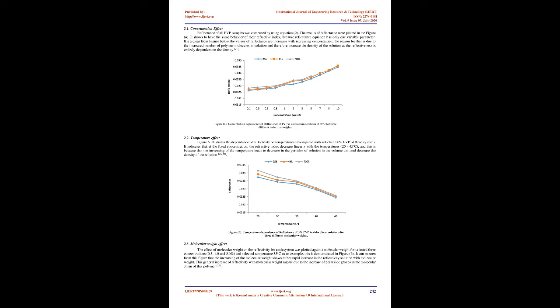3 Results and Discussion. Refractive index has been measured for 10 different concentrations, 0.1 to 10%, of PVP in chloroform solution for the molecular weights 25K and 44K, and for 7 concentrations, 0.1 to 5.0%, of PVP for the molecular weight 700K in chloroform solution. All solutions were measured at 5 different temperatures, 25 to 45 degrees Celsius, at 5 degrees Celsius intervals.